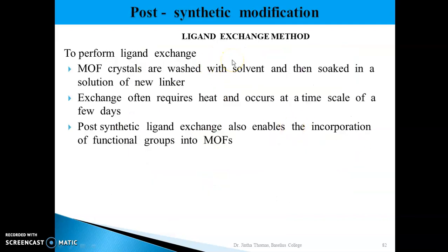In order to perform the ligand exchange method, MOF crystals are initially washed with solvent and then soaked in a solution of the new linker, the new ligand. This ligand exchange process often requires heat, and it occurs on a time scale of a few days. So, we have to immerse the already synthesized MOF and new linker in the solvent for a few days.